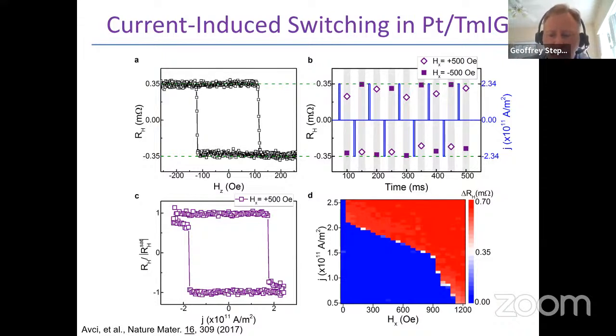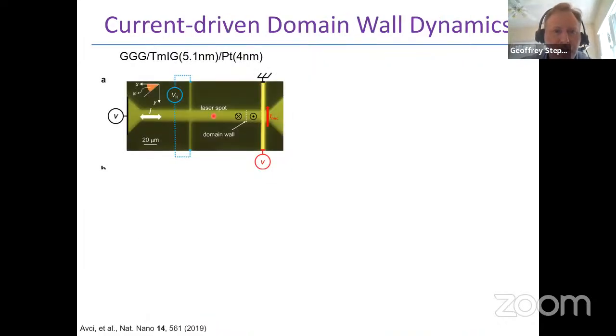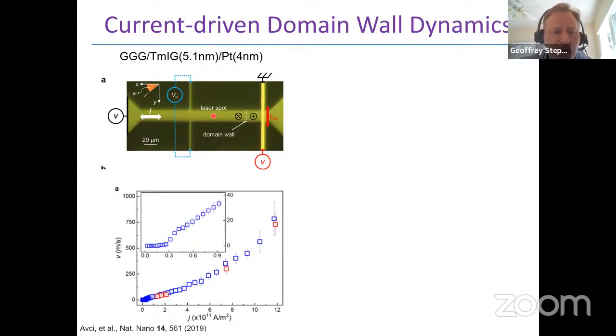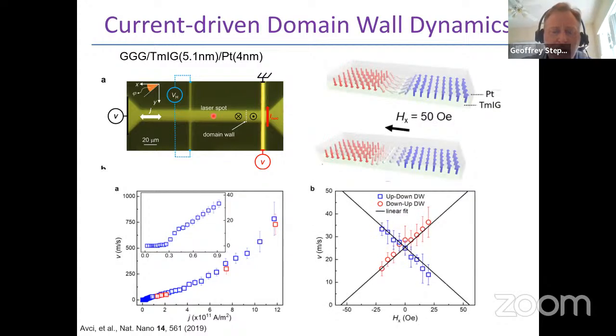That then gives hope that you could also drive domain walls and other textures in these materials, and that's exactly what we have seen. So by making racetracks of thulium iron garnet with platinum on top, we've shown that you can drive domain walls to reasonably high velocities at reasonably low currents. And while I won't go through all of the details, we've shown that in these kinds of structures there is a Dzyaloshinskii-Moriya interaction, so an interfacial DMI, that stabilizes Néel walls that can be efficiently driven by spin orbit torques in these materials. And that was a big surprise to us.